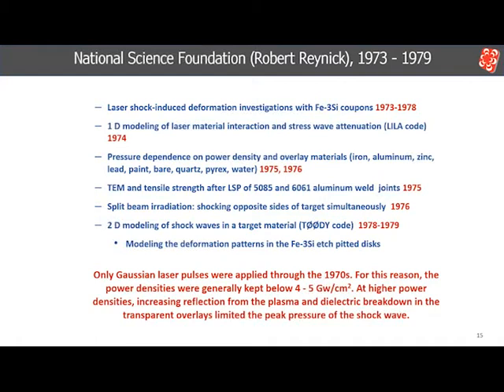I will note here that all of the laser shots through the 1970s used a Gaussian laser pulse. Because of this, the applied power densities were generally below 4 to 5 gigawatts per centimeter squared. Above this range, there was increased reflection of the laser beam from the hotter plasma and greater risk of dielectric breakdown in the transparent overlays, limiting the peak pressure.